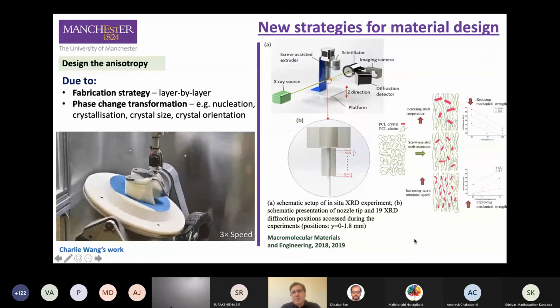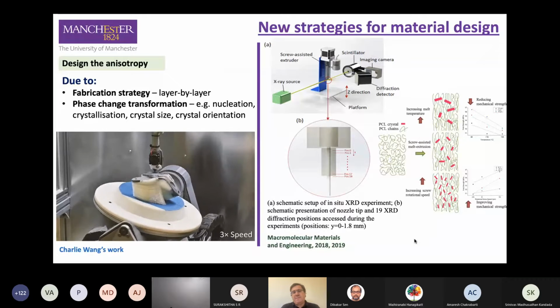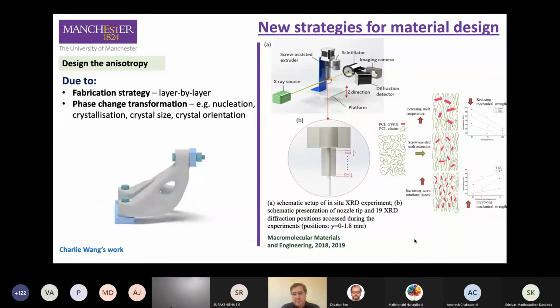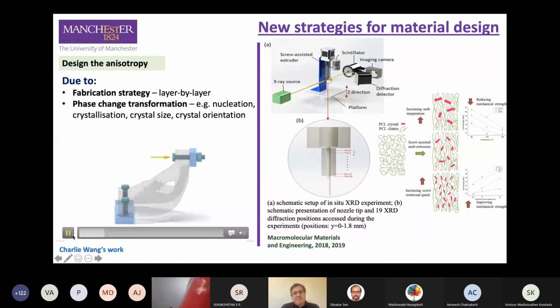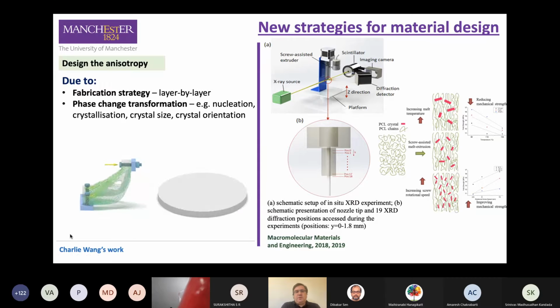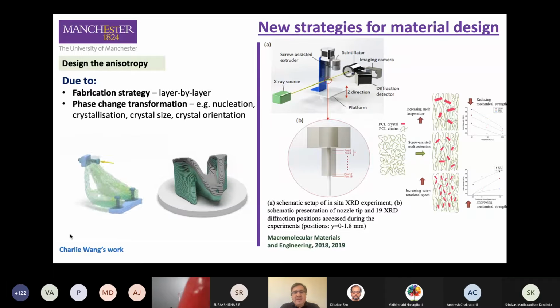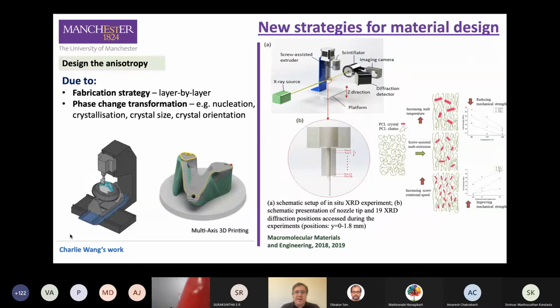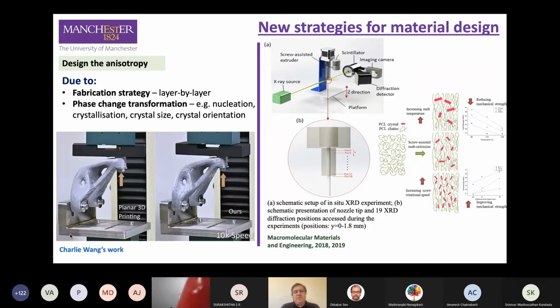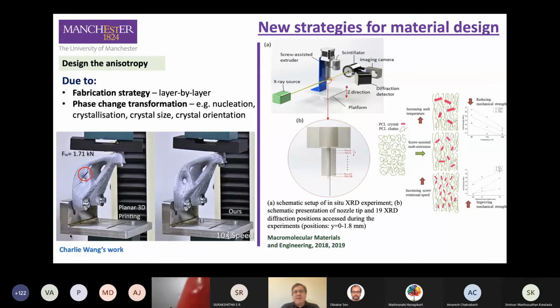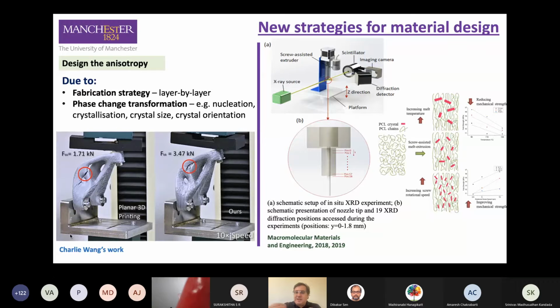Well, one of the problems that we have in additive manufacturing is, as you know, related to the anisotropy. And anisotropy in additive manufacturing is due, first of all, to the fabrication strategy, because usually we create parts layer by layer, but it is also related to the phase change transformation that the material suffers during the printing process. The material is in the solid state, we heat the material, and then we cool the material again. So due to this morphological transformation of the material, it is difficult to control, for example, crystal orientation, crystal size, and crystal growth.